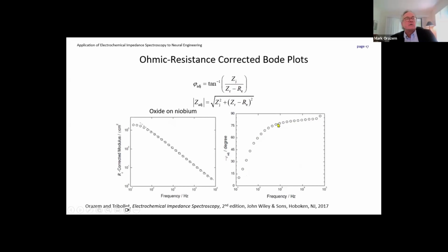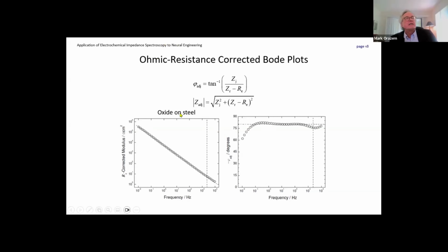And in fact, we use a model which is called the Young model, which involves an exponential distribution of resistivity to fit this data. But when we look at the oxide on steel, what we see is that in this frequency range, we see effectively a constant. So we're seeing a constant phase element behavior in this region.